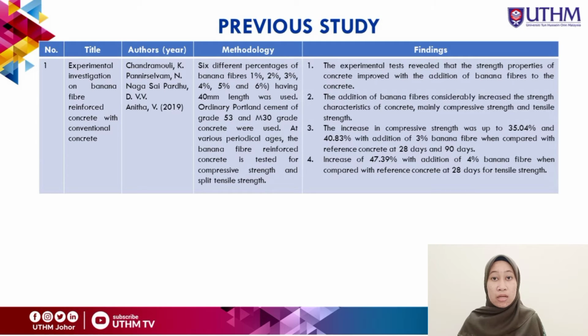And the finding is, the experimental test revealed that the strength properties of concrete improved with the addition of banana fiber to the concrete. The addition of banana fiber considerably increased the strength characteristics of concrete, mainly compressive strength and tensile strength. The increase in compressive strength was up to 35.04% and 40.83% with addition of 3% banana fiber when compared with reference concrete at 28 days and 90 days.